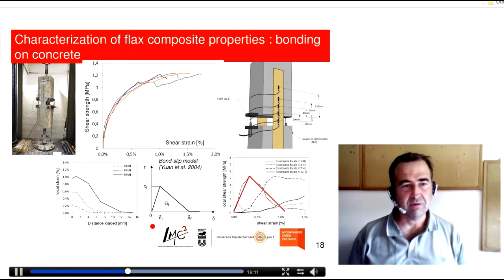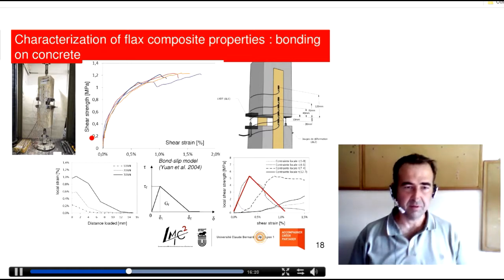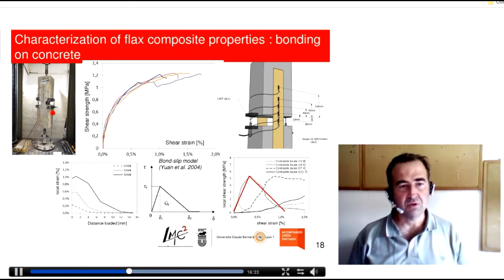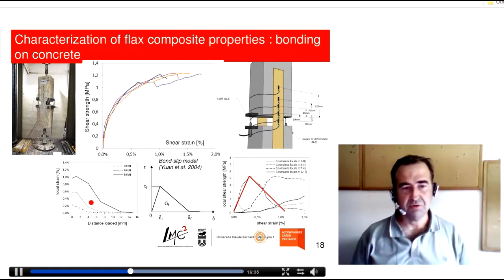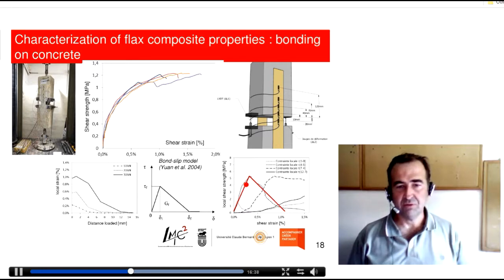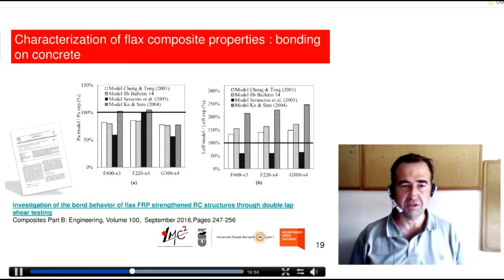Next stage was to evaluate how these flax fibers can be bonded onto concrete using this specific two-matrix polymer used in our research. We use a typical double lap shear test, and we obtain shear in function of bond slip. We can observe the local strain distribution, and then we compare this to the usual local bond slip model obtained in literature. What we can say is that more or less the behavior is very, very similar to the one that we can obtain with glass or carbon fibers, just the mechanical properties may change.